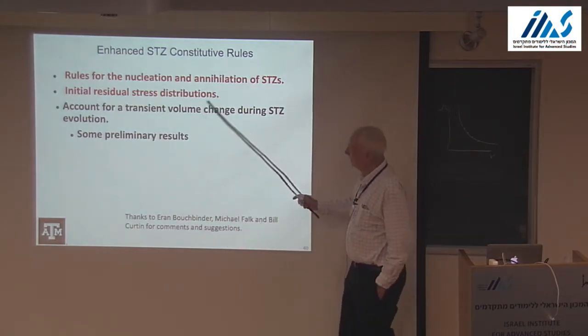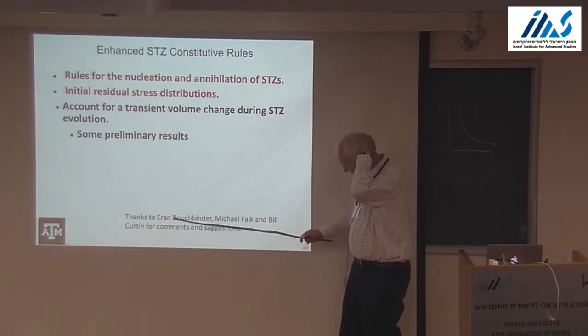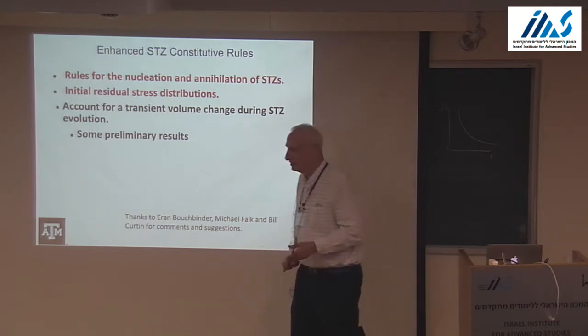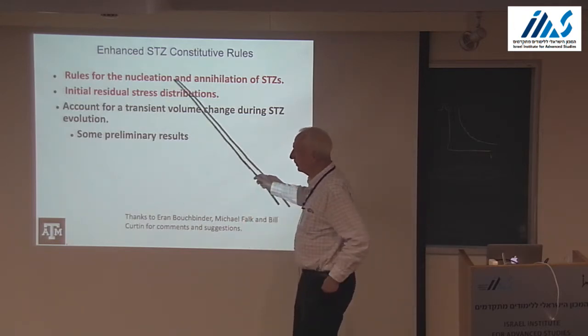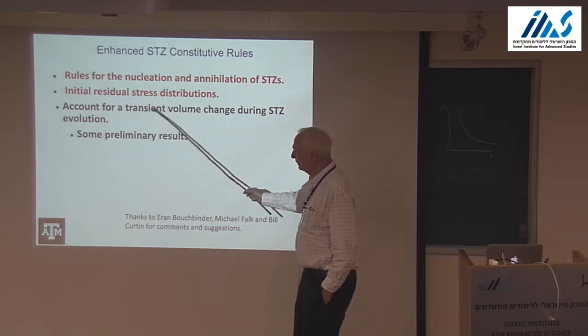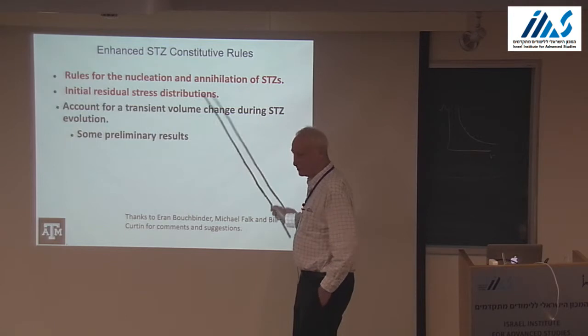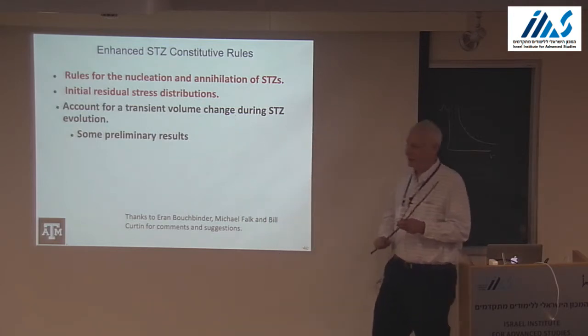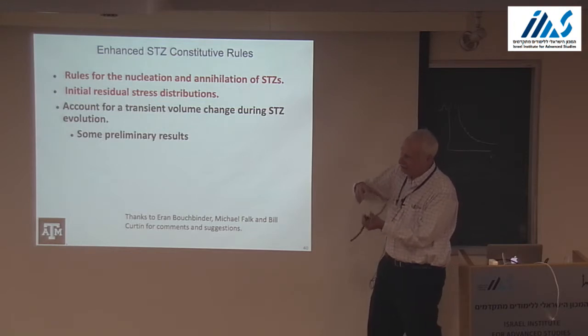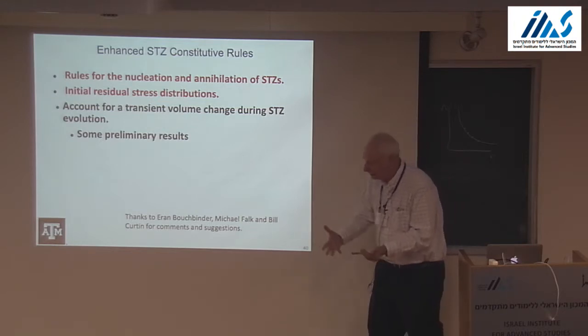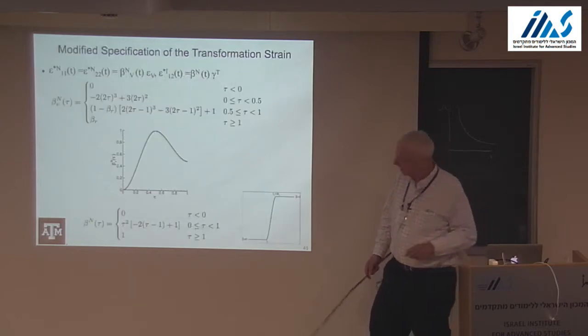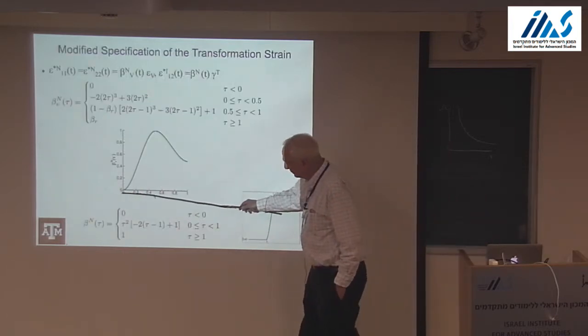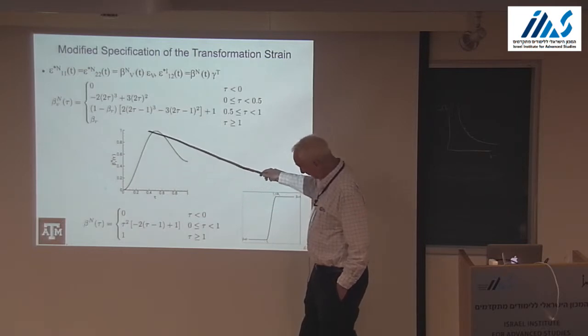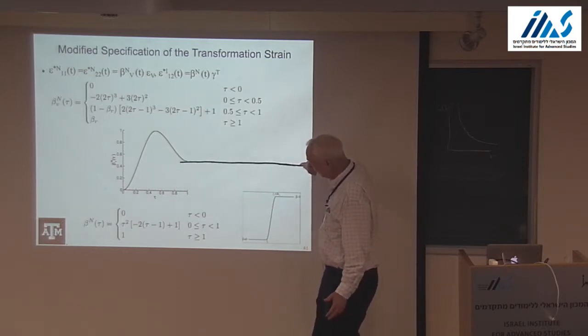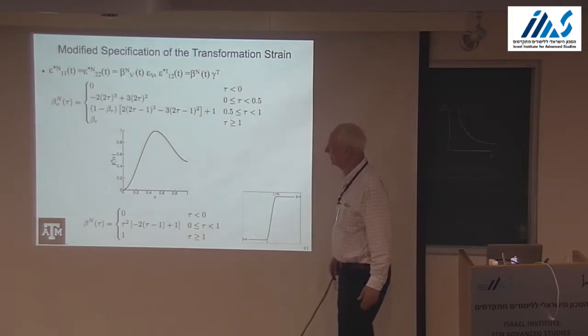Okay. So what we need, and this is actually from, we talked with Eran, we talked with Michael, and Bill Curtin, and they really encouraged us to do something more physical. And we're working on that now. But one thing we could do very quickly is account for a transient volume change. There's some indication that as these things shear, they expand, but then they go back. So we modeled that very simply by having, as a function of the transformation time, it goes up to some peak volume change, comes down, and we can leave a residual volume change or have it go back to zero.